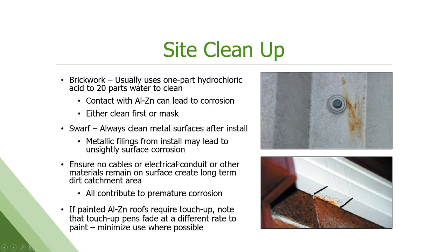So it's not the panels rusting, it's this debris on the surface rusting, which isn't going to cause the roof to fail by any means, but it looks terrible because once it starts to corrode, it leaves a red stain that's very, very hard to get off, almost impossible to clean off. So you need to make sure that the installers are cleaning all that up every day, washing it down good so it doesn't stick. And then again, you want to make sure that you don't leave anything laying around that's going to cause corrosion long term. Get everything off that roof as quickly as possible.